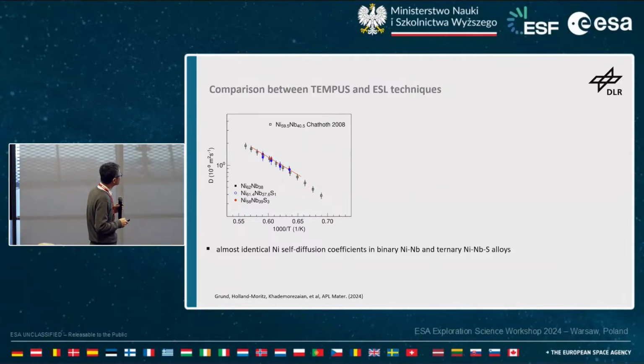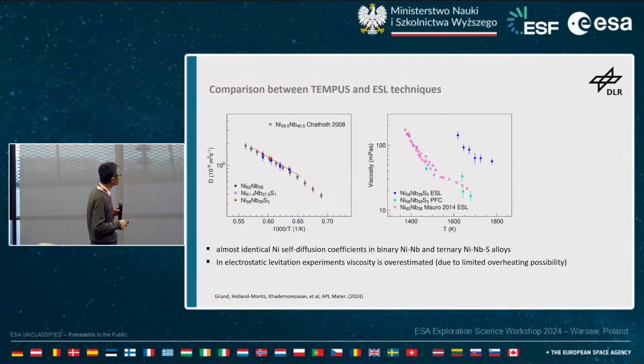Another point I want to show you is that we also have in our ground facility another levitation method, electrostatic levitation, with which you can do a similar kind of experiment. This is just to remind you that, from the transport coefficient, the dynamics of the melt is not changing a lot. So you expect that the viscosity is also similar. And this is what we get when comparing the data from parabolic flight and the ones measured in our ground facility using electrostatic levitation.